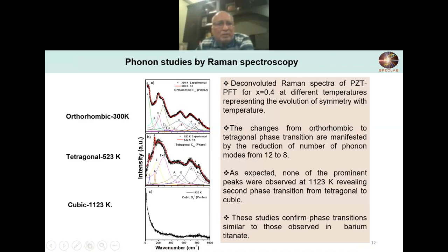We did Raman spectroscopy. We deliberately chose the temperatures so that we could be in the orthorhombic phase, the tetragonal phase, and the cubic phase. At those temperatures we took the Raman spectra of the material. It was very complicated. When we analyzed them in detail, we found 12 peaks, and then at a higher temperature at 523 it reduced to 8 peaks.